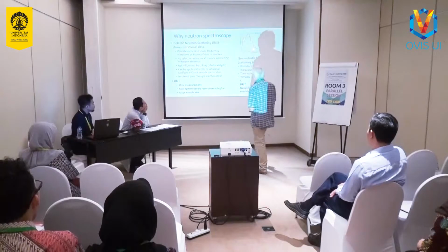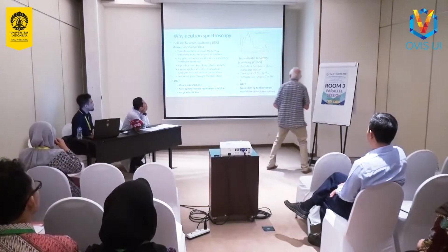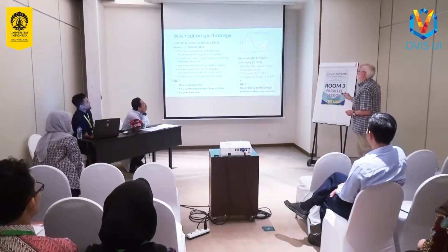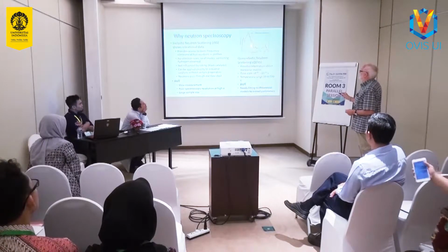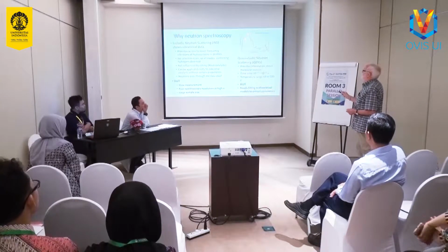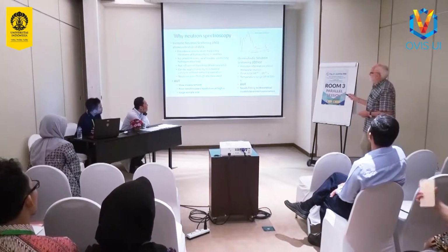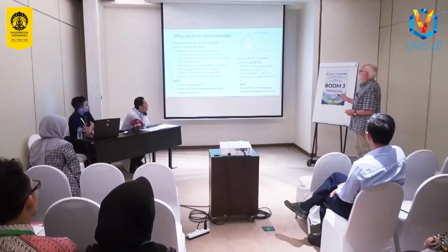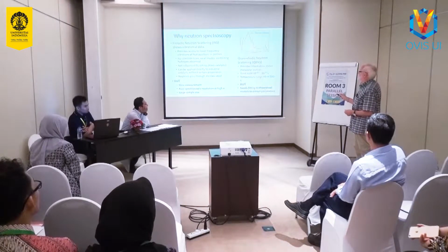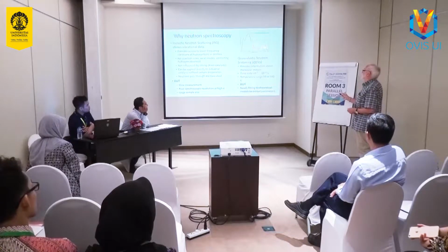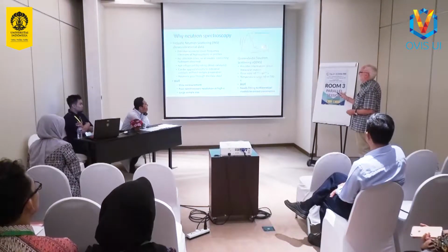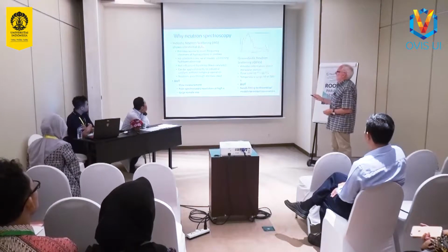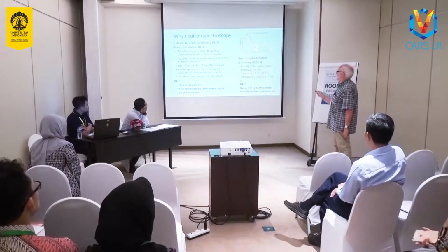Here's an infrared spectrum of a dehydrated zeolite. And you see that below about, this is a diffuse reflectance spectrum, below about 1800 wave numbers, there are very strong bands due to the zeolite lattice. That means in practice, if we're looking at adsorbed molecules, we really can't see very much in this region because these bands are too strong. So infrared spectroscopy of zeolite materials, anyway, is restricted to the higher frequency end of the spectrum. Here are the OH groups, for example, in zeolite, which are easy to see by infrared. So inelastic neutron scattering gives us lower frequency vibrations that we can't see by infrared.